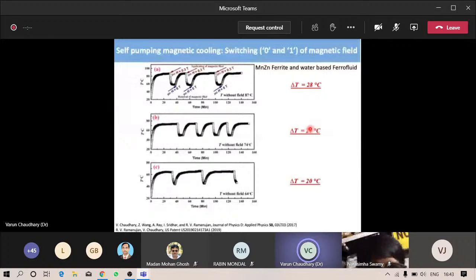Next, we checked the switching effect. And what is the switching effect? We first don't apply the magnetic field, and we check the temperature of the heat load, and in between, after let's say 20 minutes, we apply the magnetic field. And immediately, within 2-3 minutes of applying the field, there is significant cooling. And when we again remove the field, it goes back to the same position, and it shows cyclic behavior. We did this kind of experiment for different temperatures and found the same here also, that the cooling increases with increasing initial temperature, and it's a completely cyclic behavior.